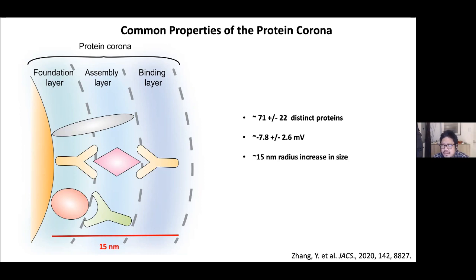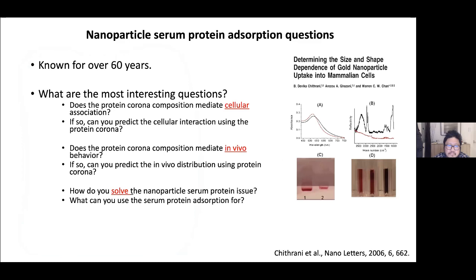We also found that if you have a small nanoparticle less than 6 nm, it may actually ride a protein. If a protein is 10 to 15 nm, that small nanoparticle binds onto the larger protein and essentially travels along with it. This is the basic overview of what we know about the nanoparticle protein corona.